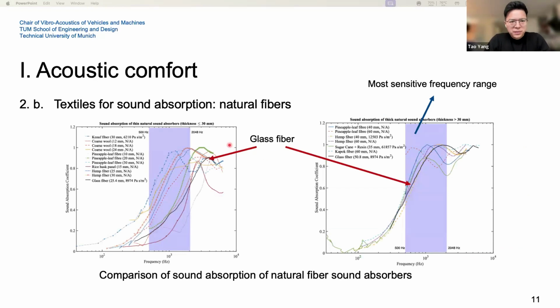In one of my review papers, I compared plenty of natural fibers with the conventional glass fibers. In the left graph, it shows the comparison between natural fiber and glass fiber with a 30 millimeter thickness. We can see plenty of the natural fibers have superior sound absorption, for example kapok fiber and pineapple leaf fibers. Then another group is the sound absorbers with thickness over 30 millimeters. Also, the pineapple fibers exhibit very good sound absorption compared to the glass fiber. It might not be very clear from your side, so if you need more data or if you are interested, just write to me. I can share the whole data.